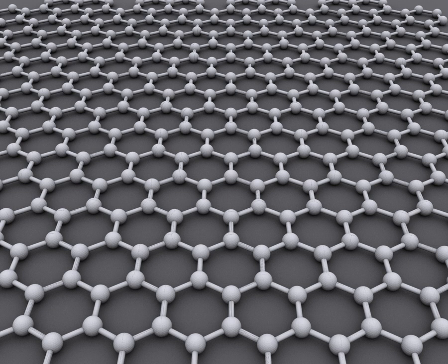Atomic resolution real-space images of isolated, single-layer graphene on silicon oxide substrates are available via scanning tunneling microscopy. Photoresist residue, which must be removed to obtain atomic resolution images, may be the adsorbents observed in TEM images and may explain the observed rippling. Rippling on silicon oxide is caused by conformation of graphene to the underlying silicon oxide and is not intrinsic.